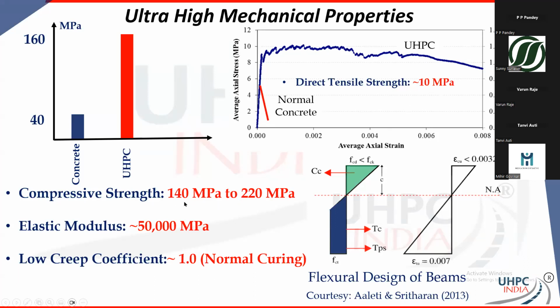Compressive strength, like I said, it's typically over 150 MPa. You will get it in the range of 120 to 250 MPa also. Elastic modulus, typically 50 GPa or 50,000 MPa, but there are UHPCs which will give you about 70,000 MPa as well, and a very low creep. So when I say a very low creep, you're talking about 1 with normal curing and almost like 0.2 with steam curing, right? Extremely low. Now, all this is a very, very good masala for long span construction, right?